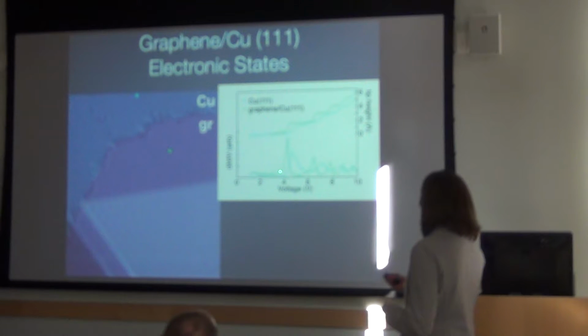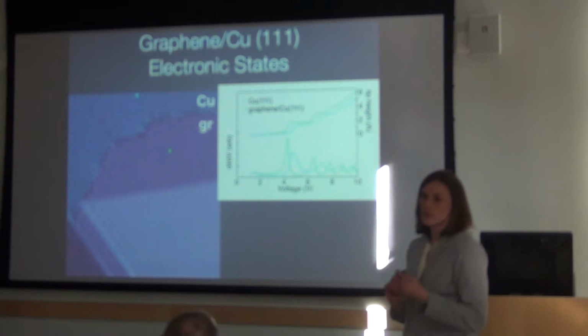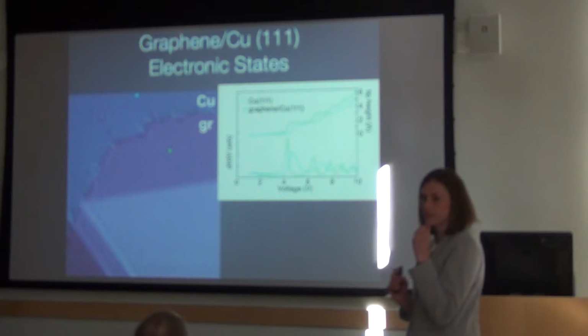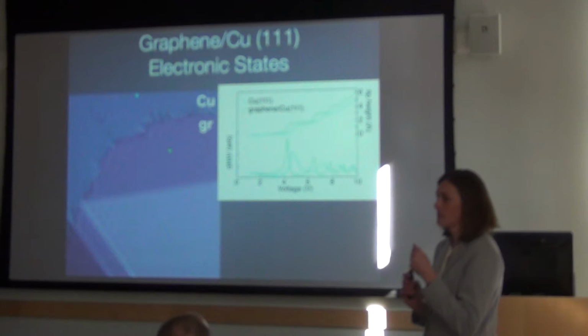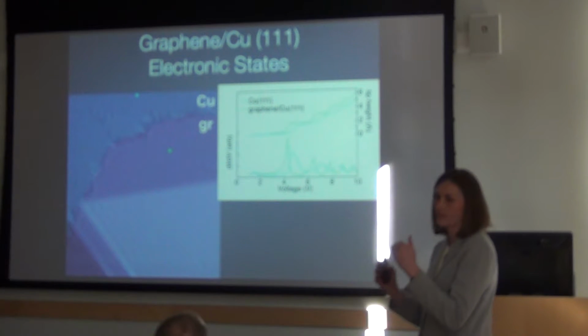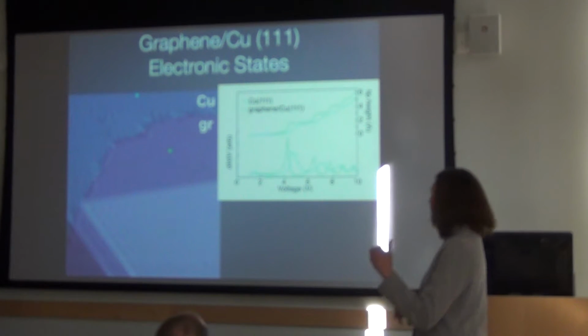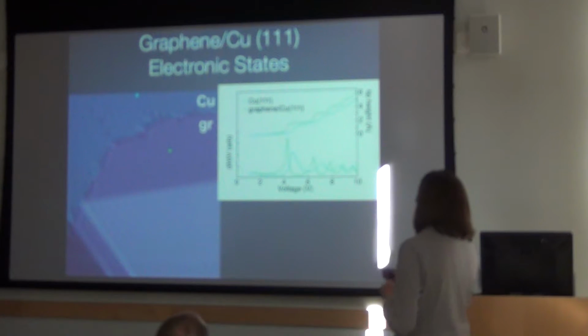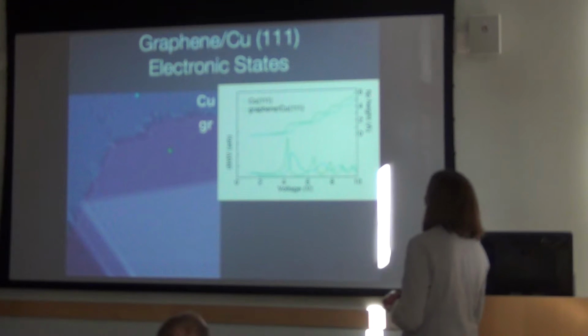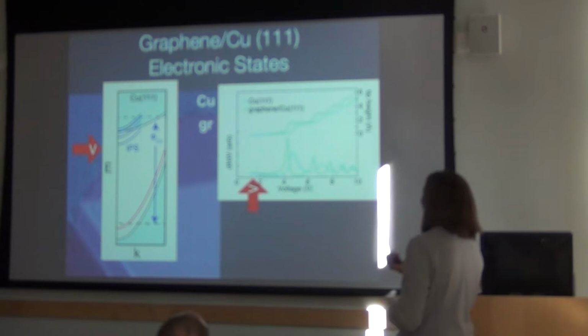And the other thing that we can see is that these resonances are much narrower. So that tells you about the electron lifetime in these states. How long are the electrons hanging around if they tunnel into the state? Because it's sort of a transient state, they have to then tunnel into the crystal itself. So we can actually get a lot of information from staring at these things. But, oh, here you go. So this is what's happening.